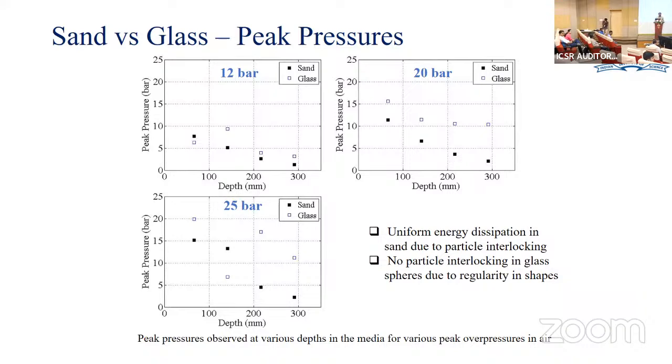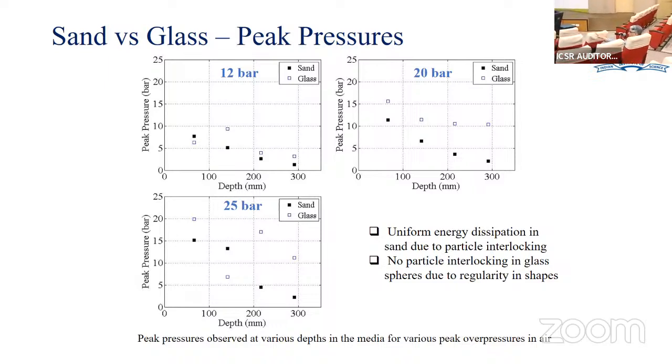We are trying a different pressure sensor. One thing is that for glass beads, the particle size is assumed to be uniform, but in sand it is not like that. In sand, the maximum particle size is 2 mm. There is a maximum and minimum. Glass is supposed to be the same. The packing fraction will be more in sand than in glass. There will also be friction between the particles in sand, but not in glass, hopefully. I think these are the things we have to consider and see why the decay is coming, and so on. Let us see that.